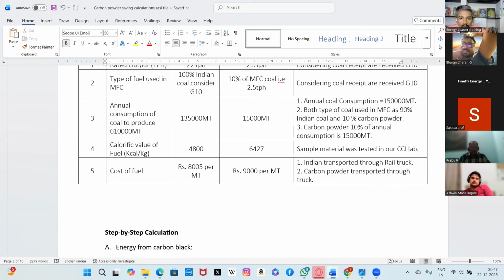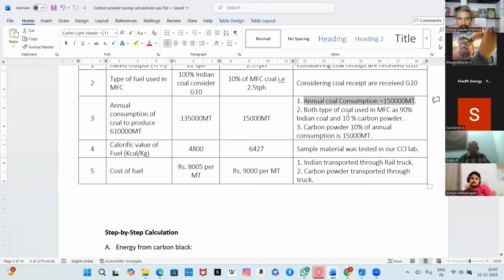As I say, the calculation I have shown here, annual consumption is 1.5 lakh metric ton. Indian coal 90% and carbon powder 10%. So of the 1,50,000, 10% is calculated as 15,000 metric ton. The calorific value of Indian coal is coming around 4,800 kilocalories per kg. For the carbon powder, it is coming around 6,427 kilocalories per kg.